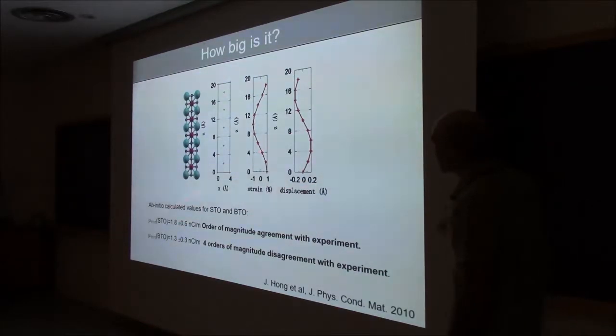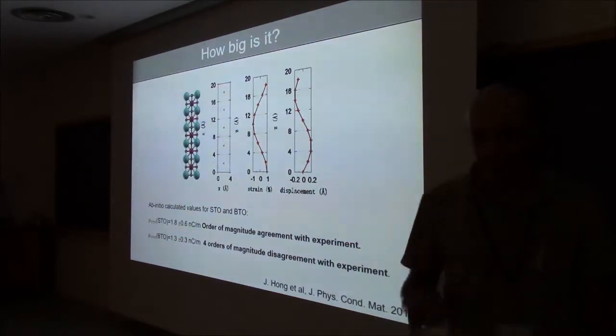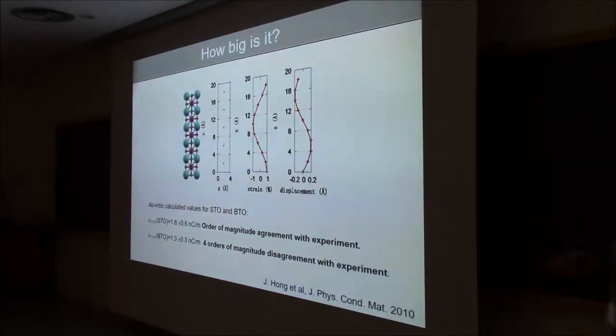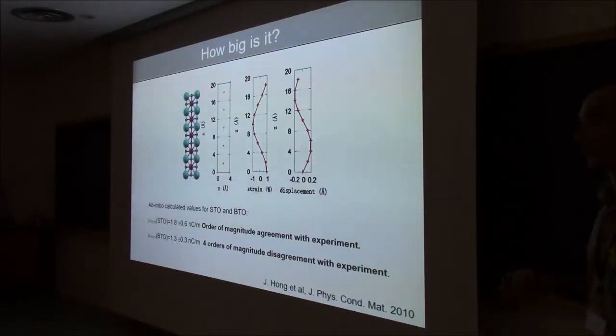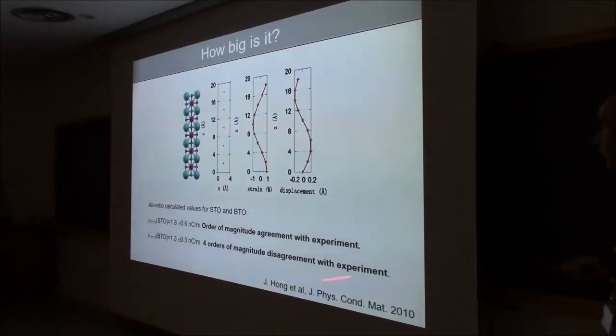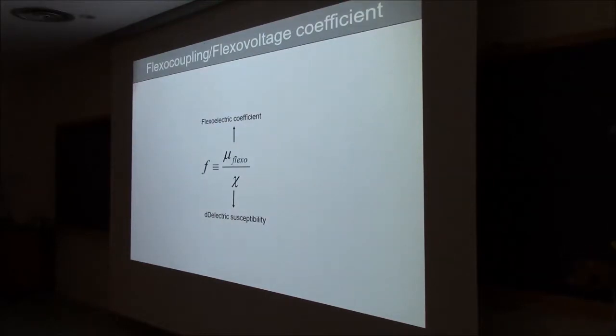When we did exactly the same trick for the BTO, however, we also got nanocoulombs per meter, and yet the experimental flexoelectric coefficient of BTO is not nanocoulombs per meter, it's microcoulombs per meter. So we had a 3 or 4 orders of magnitude disagreement between theory and experiment. And we needed to understand that.